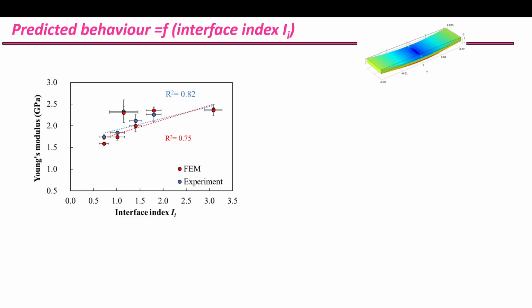In order to quantify further these effects, we sketch here the Young's modulus dependence on the interface index, and surprisingly, we see that there is a linear increase of the stiffness with the increase of the interface index. This appears to be surprising because we would think that the lower properties at the interface would trigger a lower behavior, but in this case we see the opposite behavior.